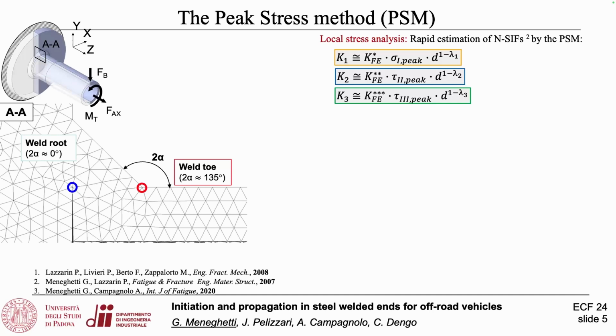If we consider a welded joint, the basic assumption in the method is to model the weld root or the weld toe as sharp V-notches, with no weld toe radii modeled in the finite element model. Then with a rather coarse mesh, later on I will talk about how coarse the mesh can be, we have to consider the linear elastic peak stresses at the weld root and weld toe.